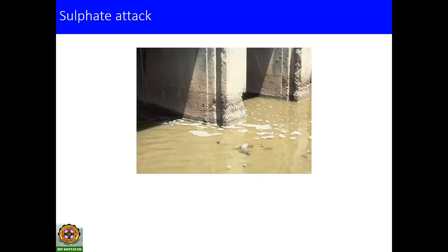Now this one is the sulfate attack, in which the sulfate from the exterior environment enters the concrete system. It reacts with the C3A and finally forms ettringite at a later age. This ettringite formation, or delayed ettringite formation, is again a volume expansive process which can deteriorate the matrix. Also, it can crack. So that is yet another deterioration mechanism of concrete.